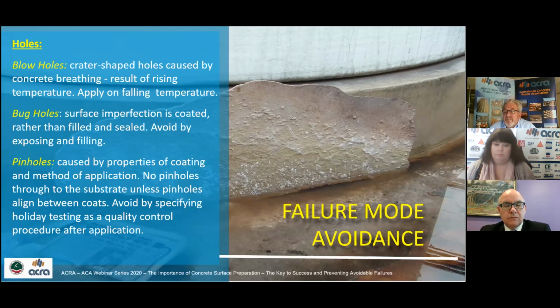This can be avoided by applying coatings and repair materials, or at least a primer or a seal coat, as the concrete has reached its maximum temperature. In other words, late afternoon when the substrate temperature is falling, it's the best time to do it. Once you get your first coat on, your prime coat on, check for blowholes and correct those before you put any further coating on it.